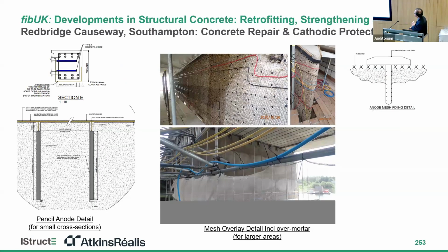These are a couple of typical standard details of the installation of the discrete anode, for example, on the left. You could see two rows of anodes installed into the crosshead or part of the bearing shelf as well. For the large surface areas, you could see the leaf pier has been surface prepped using water jetting, and then the titanium mesh has been pinned to the surface using plastic pins. Once all the cables are installed as well, the whole thing will be covered in a spray-applied mesh and overlay system, and the photo in the middle is the final product ready for energization and operation.